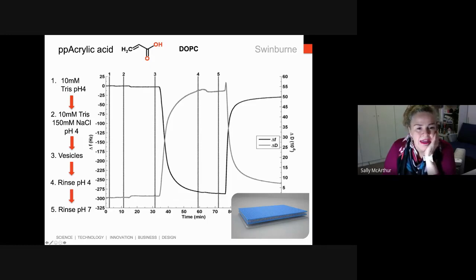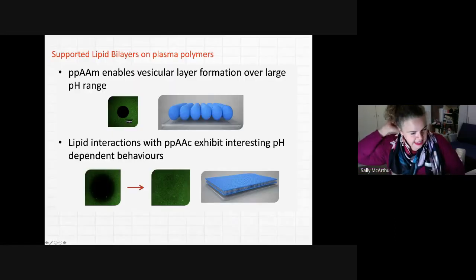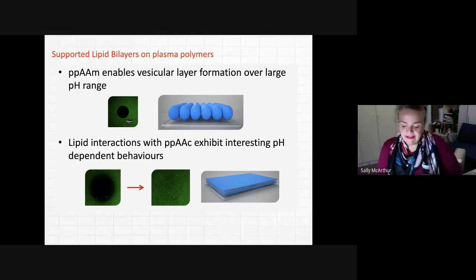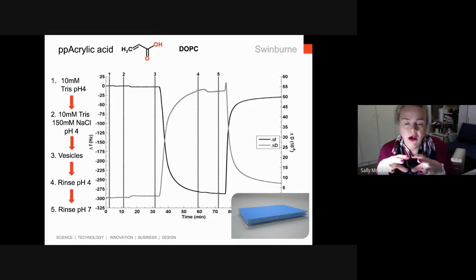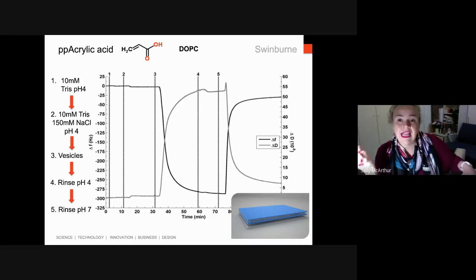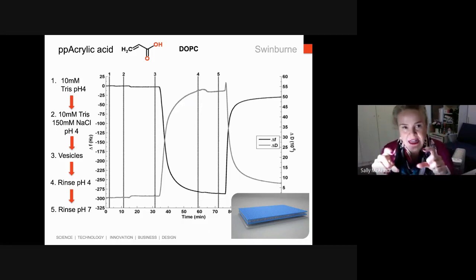Now, the interesting thing is, sorry, I've missed a point. We rinse here at pH 4. That's it here. At this point, there's no change. If we rinse at pH 7, what we actually see in this spike, sorry, I haven't presented this data for a little while, is that yes, the vesicles are leaving the surface, the surface mass comes down, and the dissipation comes down as well, indicating that now, rather than having vesicles on the surface, what we've got is the vesicle collapse on the surface, and we've validated this through other ways.